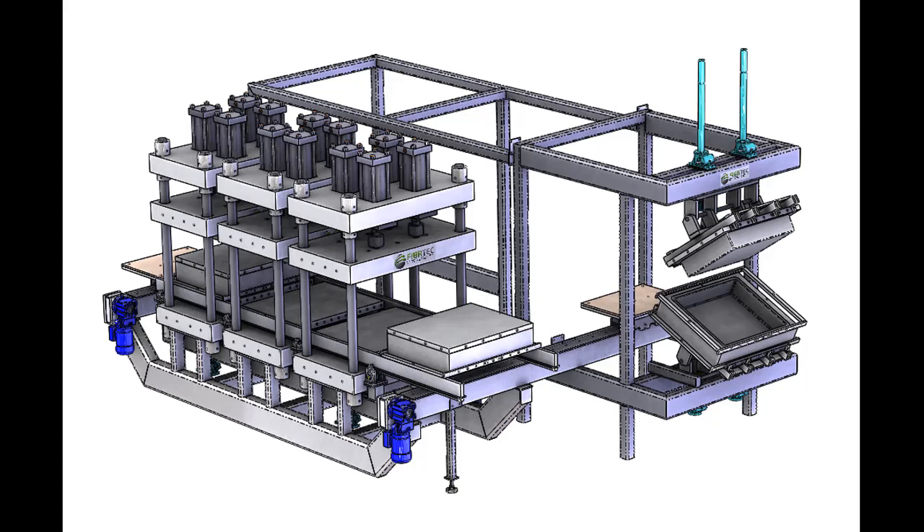We have discussed the making of FiberFlex SMC and how to create a mold charge or preform. The next step is to mold the part. This process requires pressing in matched metal molds after heating the FiberFlex SMC preform above the resin melt temperature. Once the mold is closed, a cooling process is applied until the resin has cooled to a rigid state and the part can be ejected. Commercial options for compression molding systems include preheating preforms, rapid mold heating with induction heat, and robotic material handling. These systems can cycle parts with low mass in as little as 20 or 30 seconds, though very large high mass parts can take several minutes.